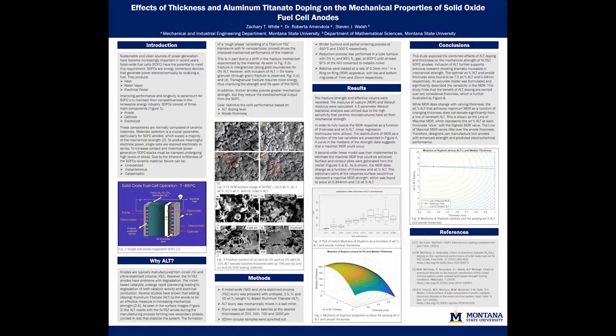On the x and y axis, we have the weight % ALT and thickness, respectively, with the modulus of rupture on the Z. The modulus of rupture, or MOR, is a measure of the bend or flexural strength of a specimen. The model predicts that a maximum MOR does occur in the variable space, which was found to be at a weight % of 7.5 and a thickness of 0.344 millimeters. The model supports previous research on the mechanical benefits of ALT and accurately models the combined effects of thickness and weight % ALT on the MOR.